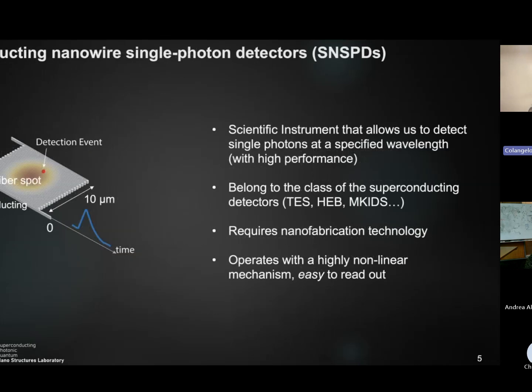However, we do have something really good, which are known to be the superconducting nanowire single photon detectors, or the SNSPDs, which are the detector of choice for most of the quantum information science applications. These are based on superconducting nanowires, where the nanowire is actually meandered in this 10 micron by 10 micron active area, and an optical fiber spot is projected onto the active area, and a single photon generates an output electrical pulse.